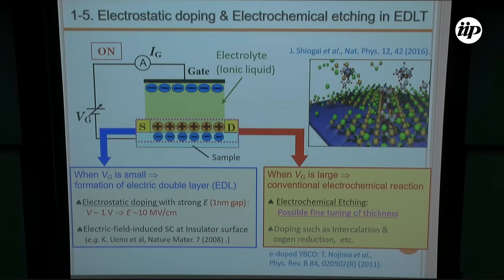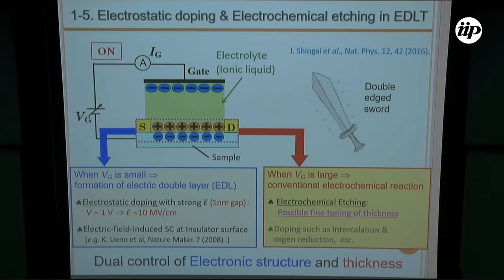And in the case of iron selenide, we found that this electrochemical reaction can be used as a very fine etching tool, based on the weak layer coupling due to the van der Waals coupling. Okay, so now this EDLT is a convenient tool with dual control of the electronic structure and thickness, like a double-edged sword.